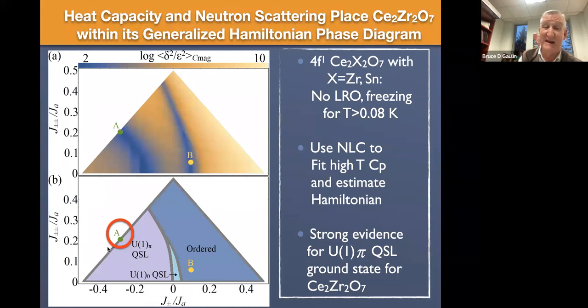So position A is where we tentatively identify cerium zirconate, and it lies well within what's referred to as a U1 pi quantum spin liquid. So this is a quantum disordered ground state. This other region here, where we have the secondary minimum, this would give you an ordered state, and there's a variety of reasons why we can discount this, but among other things, it would be expected to give you a phase transition as you lower the temperature.